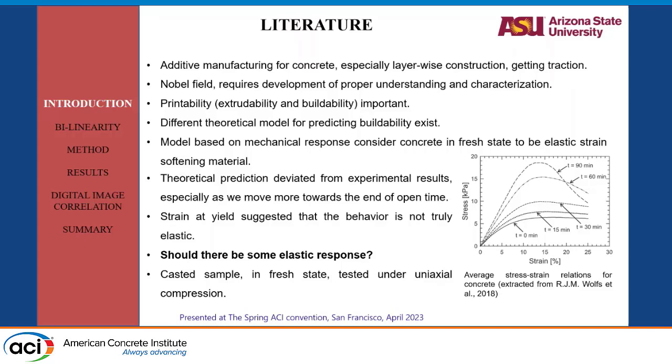Because when you print, the extruder is usually rotating the mix. So the mechanical characteristics that it gains are not always the same as the initial test results. The structuration keeps breaking in the matrix, so you have to be able to characterize it in those terms.